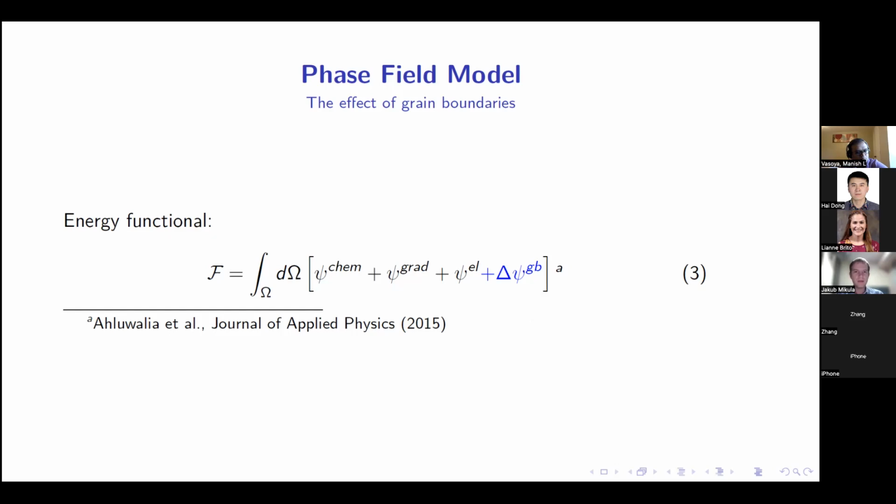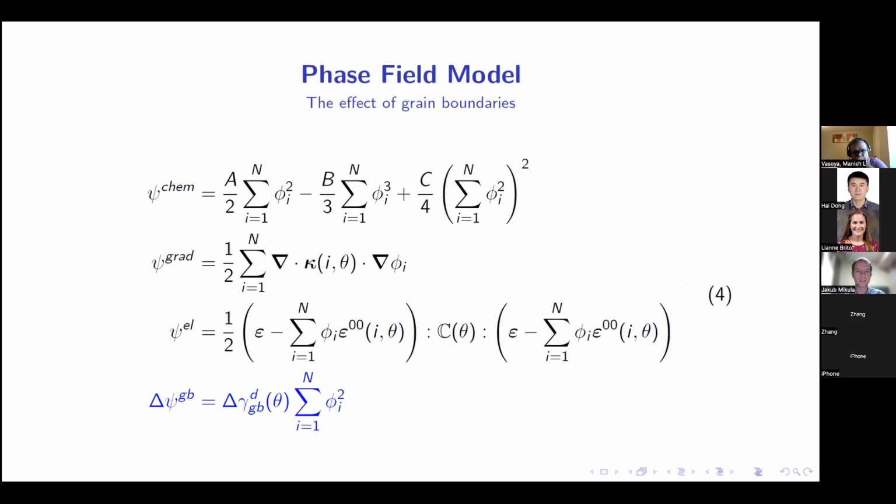But if the grain interior would transform into the martensite, then we end up having the austenite-martensite interface at the grain boundary, and then this term will come into play. Because of the increase of the total interface energy with decreasing grain size, we may actually suppress the phase transition completely. So this is how we can incorporate this effect thermodynamically within the total energy of the system.